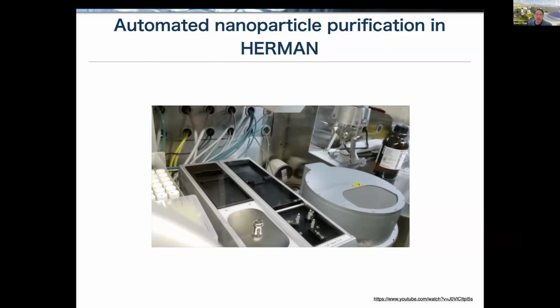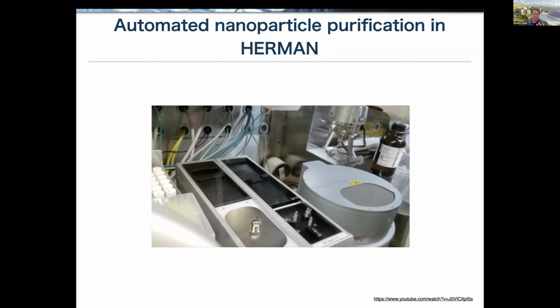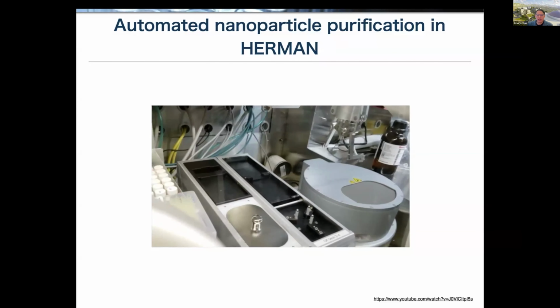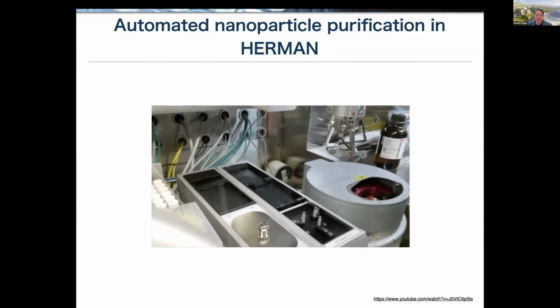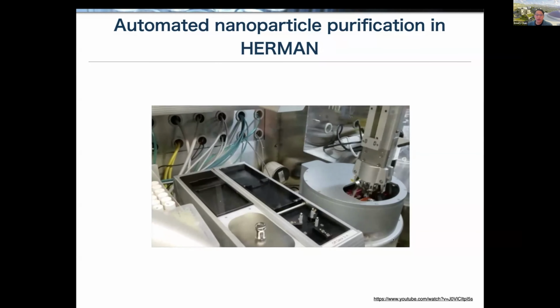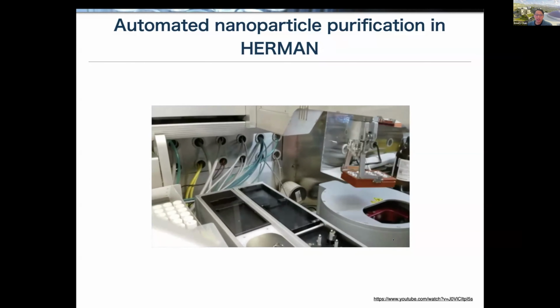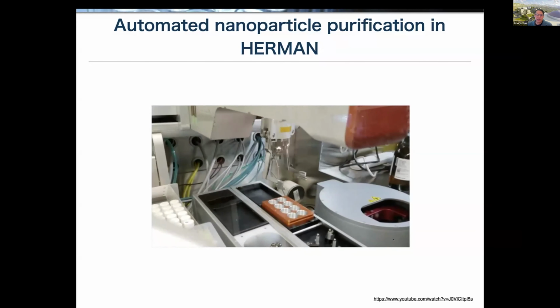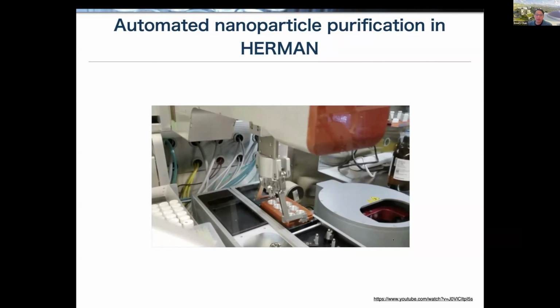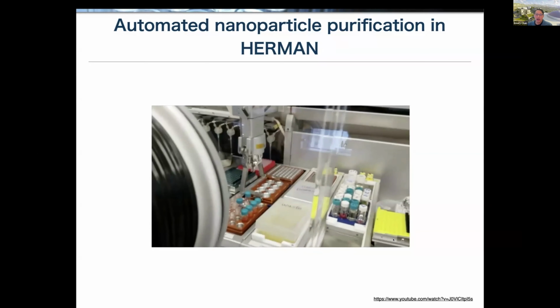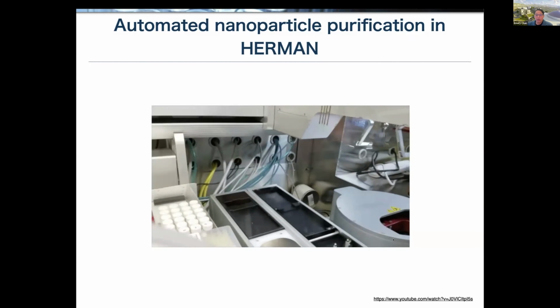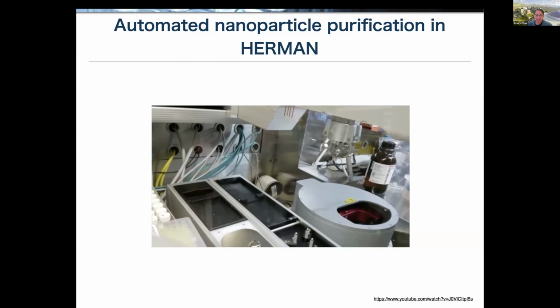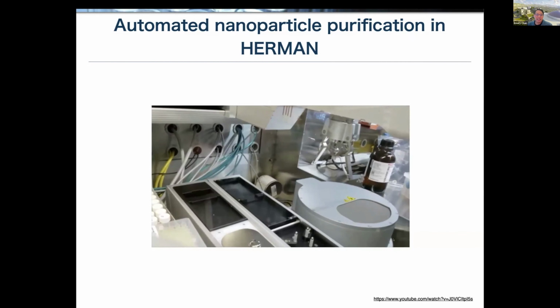And so normally what we would do is that your reaction is this soup of nanoparticles and solvent and reagents. And so we add an anti-solvent to crash out the nanoparticles from solution. And after that, you need a centrifuge to make a pellet at the bottom of your vial so that you can decant all the supernatant. So having automated centrifuges on a robotic deck is really important for systematizing this really fussy purification process.